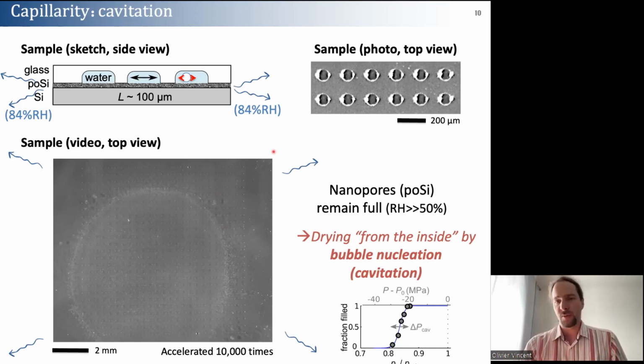So it depends on the humidity. And I think the moment at which the critical radius reaches the size of the pores, which is a few nanometers, it should happen around 40% relative humidity. So way lower than that, but it's true that it's an effect of comparing the critical nucleus to the pore size, basically. Okay, thank you. Sure.